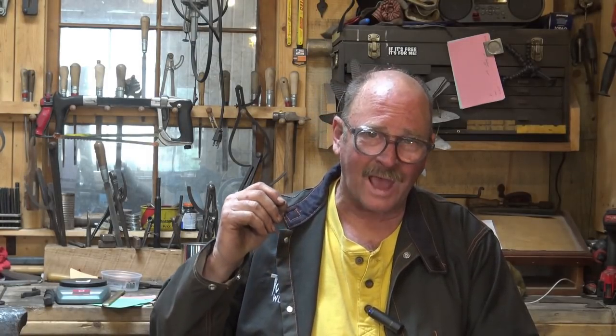But for the 5160, the S7, and the H13, and who knows how many other steels, it doesn't work. Those steels were 300 or 400 degrees below their critical temperature when they lost magnetism. So bringing them up another 100 degrees still did not reach critical temperature. And we will try to define critical temperature and what really is happening at critical temperature in a future video, when we start getting more technical and much more boring. But for now, that's the temperature that you should be quenching the material in the proper quench medium.